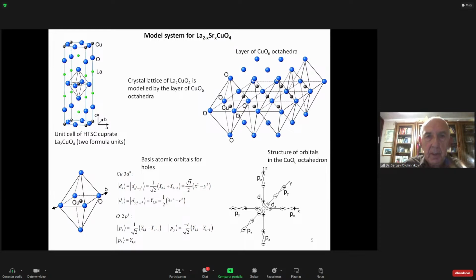To understand this anisotropy of the gap, we are doing electronic structure calculations for La2CuO4 for different doping. It is a well-known problem that the material is strongly correlated. So standard LDA or density functional theory calculations are not valid because of the strong electron correlation. So many years ago, my group developed the generalized tight-binding method to calculate electronic structure with strong electron correlation. The idea is the following.